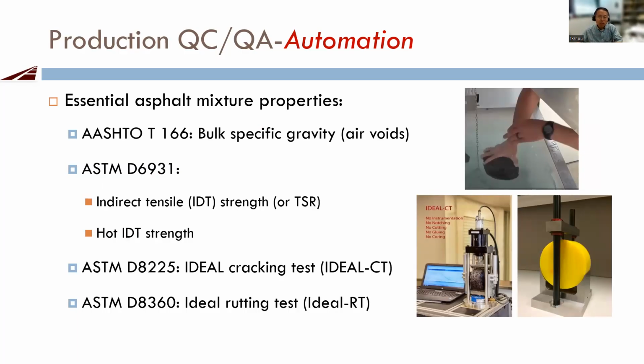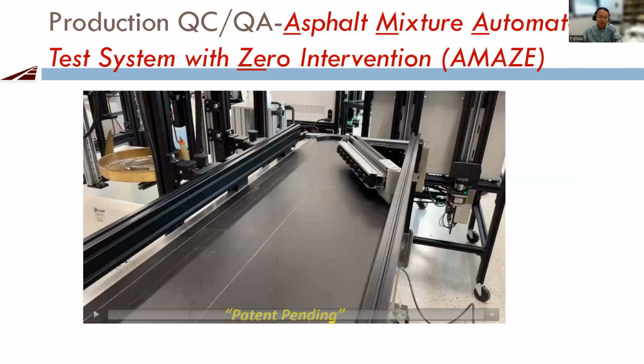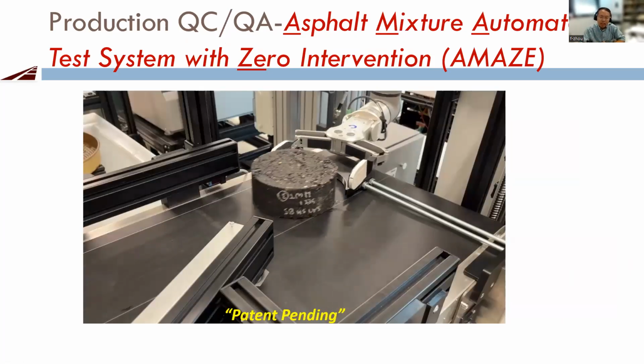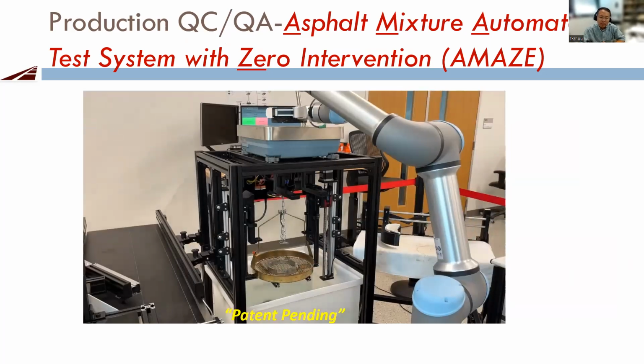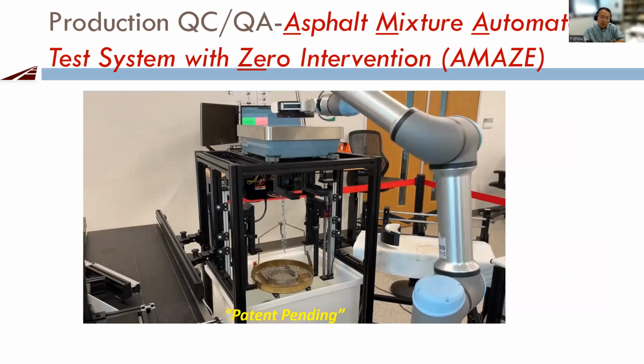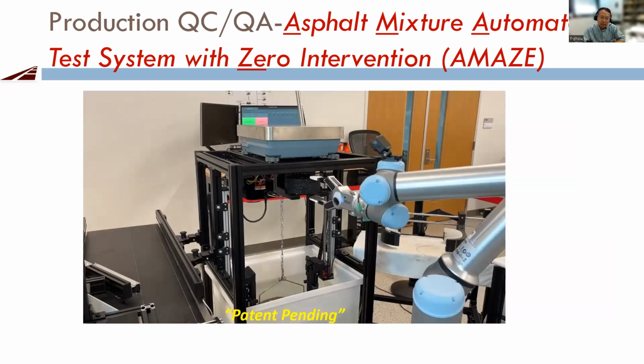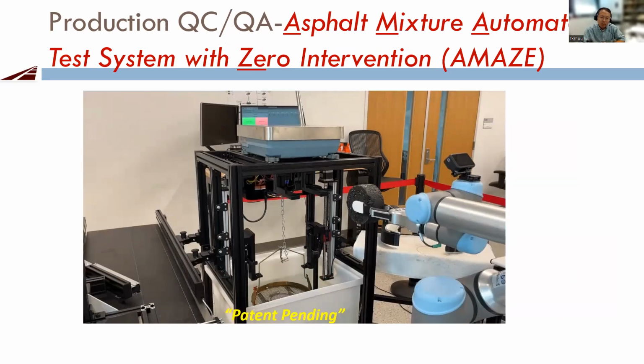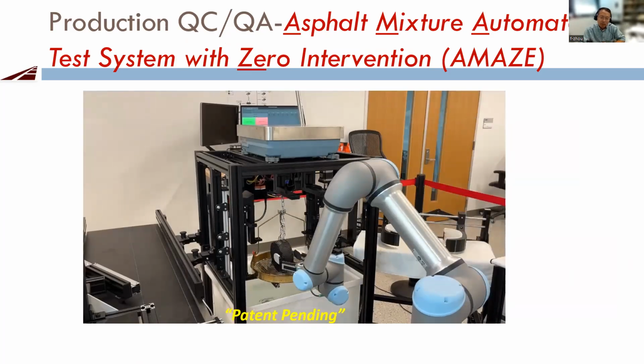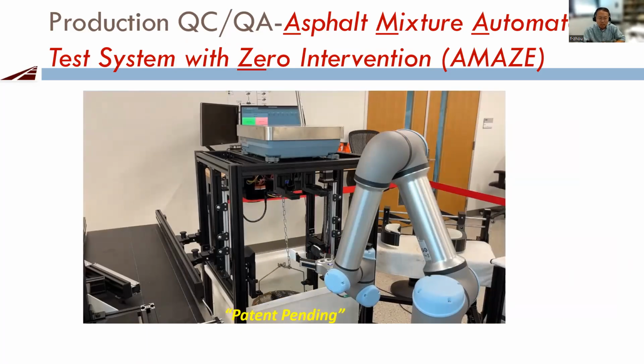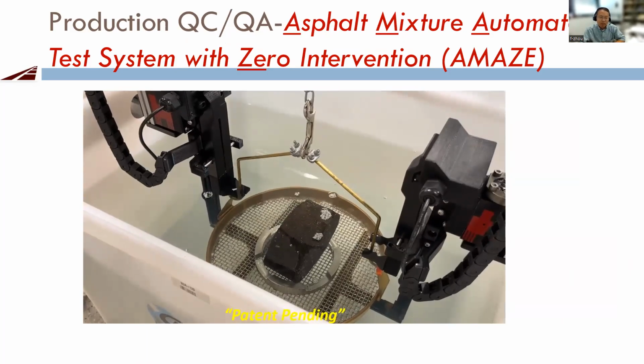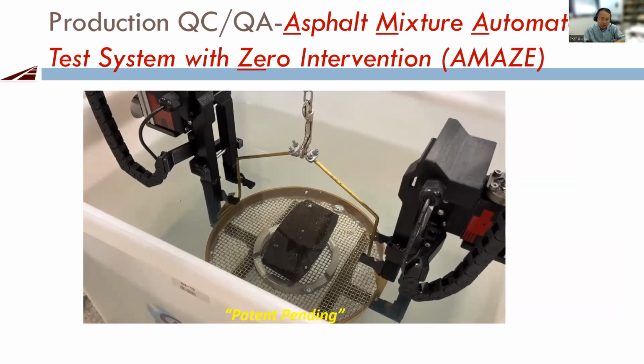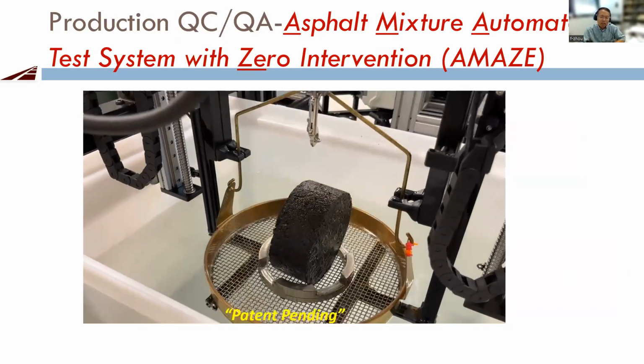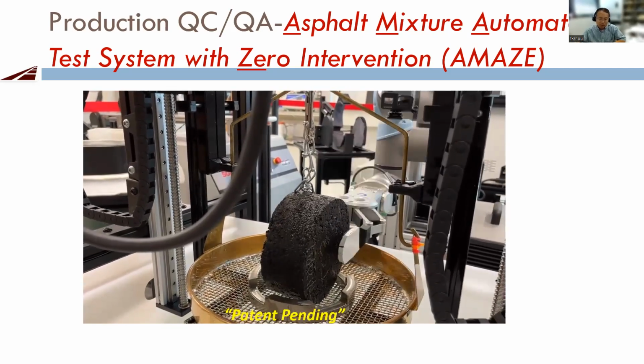The next slide, I'm going to show you a 2-minute video. You can see the process of this automation. You put one sample on this conveyor belt, and the robot picks it up and then measures the air void. Right now, they're measuring the dry weight, and then they're going to measure the sample weight in the water. They put the specimen into the basket, lower it down, and let it stay there, say 4 minutes based on the test procedure. But for this video, we just speed it up very quickly to save people's time.